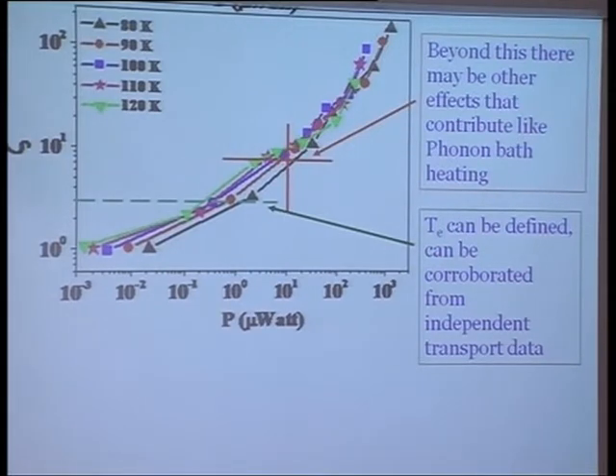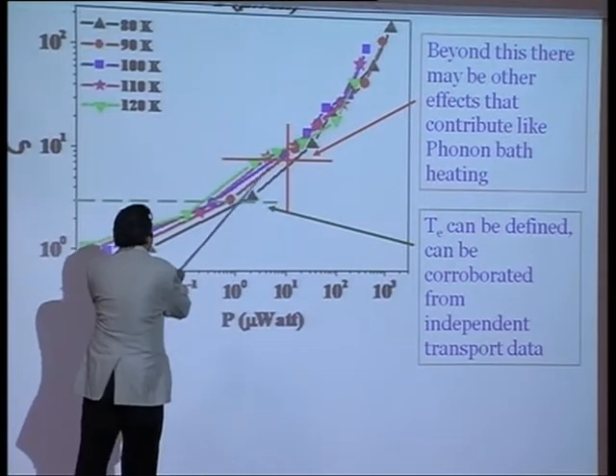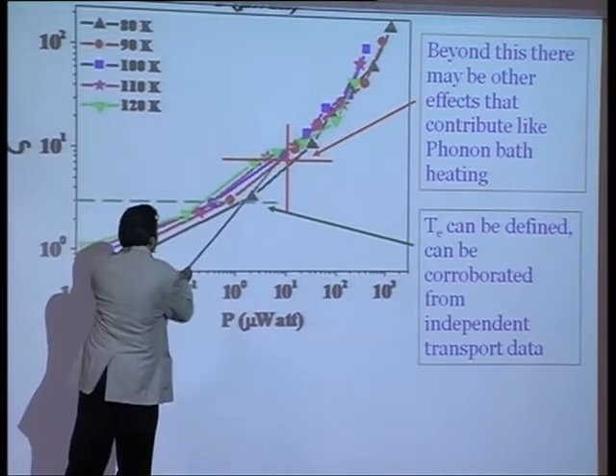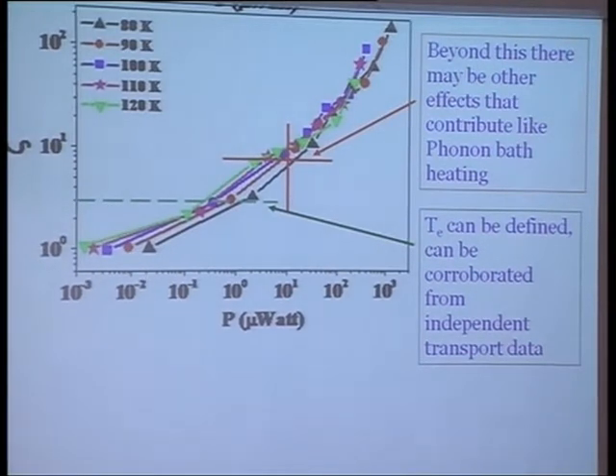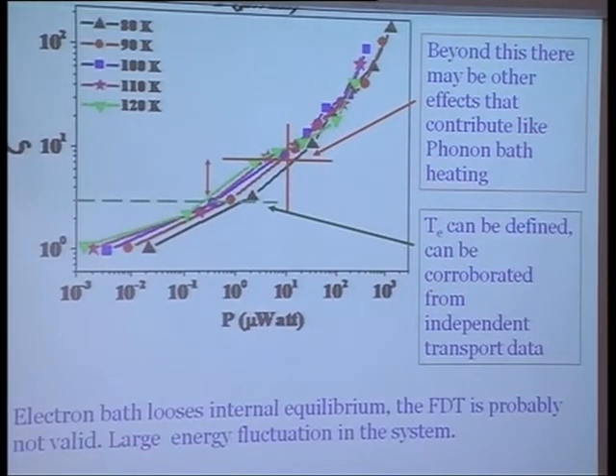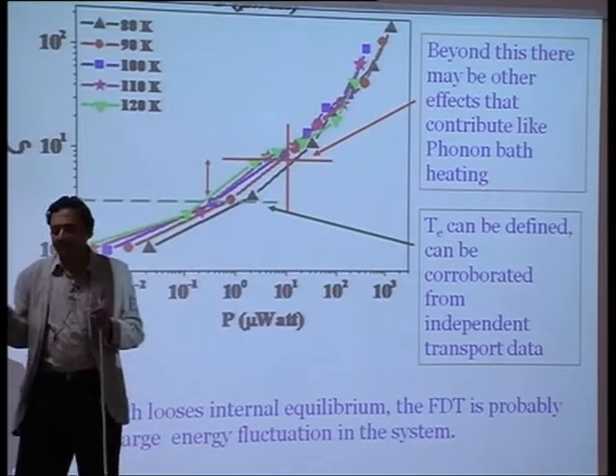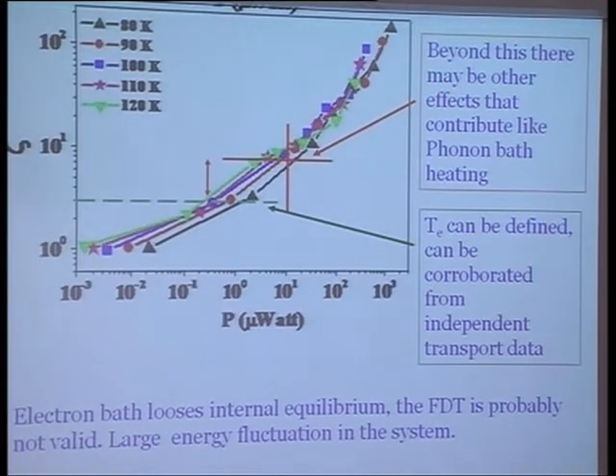But if I go to very high power, then of course there are a lot of heating effects and all that. But what about this region where disaster does not happen and we are still in some kind of defined region? That is the region I'm talking about. And this is the region where we feel that the electron has lost internal equilibrium and there is nothing called electron temperature anymore. Now we have looked into the relaxation of the voltage in that region and we find that it has a very long tail, sometimes lasting for hundreds of seconds if you change the current. Things have really become much slower, much more sluggish, and are no longer in equilibrium as you would like to think.